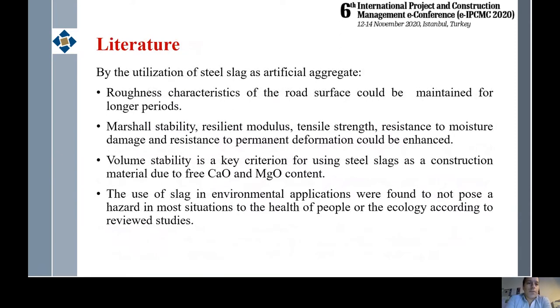We have some results from the literature. I want to give you the advantages and disadvantages of steel slag. The advantage: roughness characteristics of the road surface could be maintained for longer periods by the use of steel slag. Marshall stability, resilient modulus, tensile strength, resistance to moisture damage, and resistance to permanent deformation could be enhanced by using steel slag. But there are also some disadvantages.